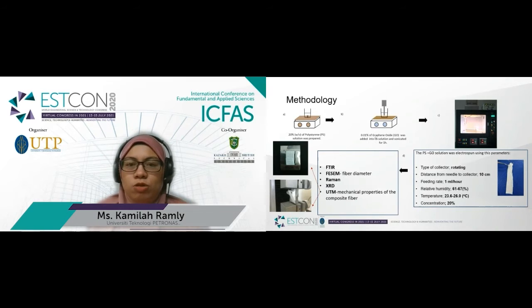The PS solution and the polystyrene and graphene oxide solution were then electrospun using these parameters. The collector used is the rotating type. The distance from needle to the collector is 10 cm. The feeding rate is controlled at 1 milliliter per hour. The relative humidity is around 61% to 67%, and the temperature was 23 to 26 degrees Celsius. This is how the final product of the electrospun membrane looked.